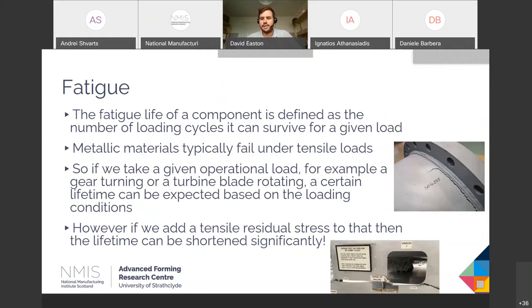So fatigue is defined really as the number of times a component can be subjected to a given load. So if we take something like a gear or a turbine blade or a shaft, if we know what the loading conditions are going to be, we can work out how long that part's going to last in service. However, if we add in a tensile residual stress, then we're effectively increasing the load on the material, as metallic materials typically fail under tension. So when we add this in, it can effectively reduce the lifetime of the part significantly in some cases. And this is fine, but it's important that we understand the presence of these stresses if we're going to accurately understand the lifetime of the material.